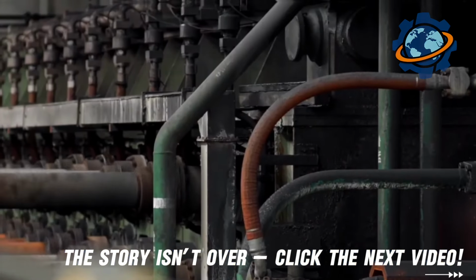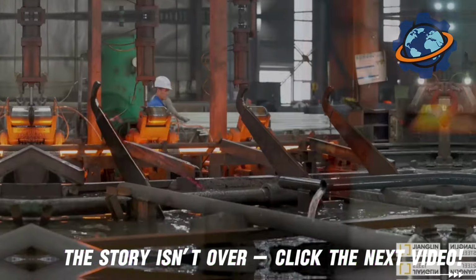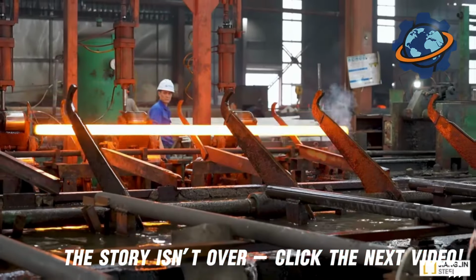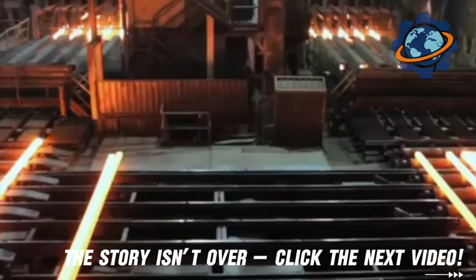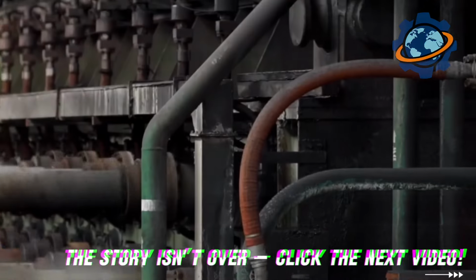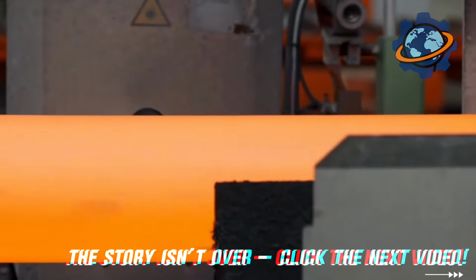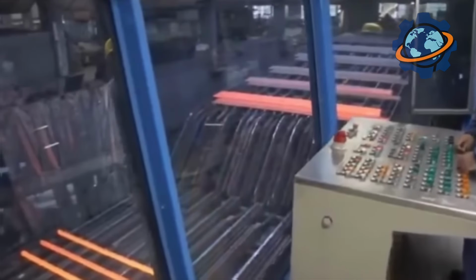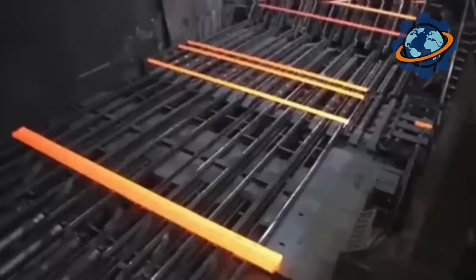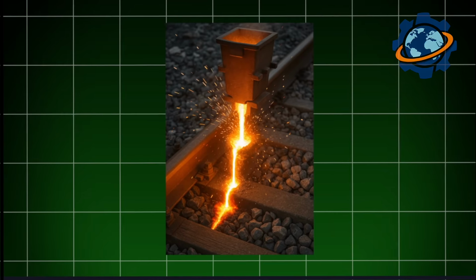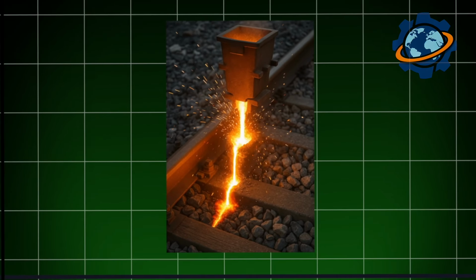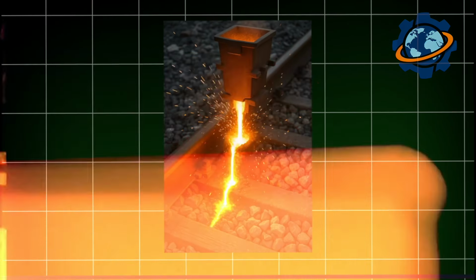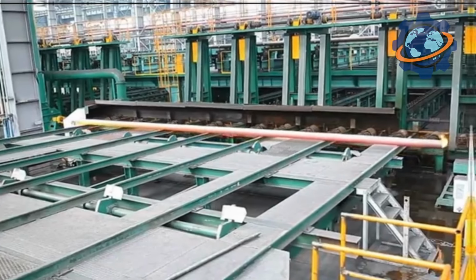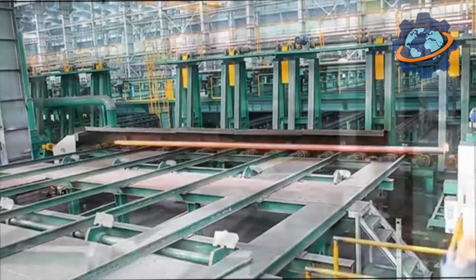To ensure a smooth, bump-free ride at high speed, individual rails are welded into long sections, up to 400 meters without a single joint. The main method is thermite welding. In a special mold between two rails, a gap of a few millimeters is left. A molten steel mixture, created by the reaction of powdered aluminum with iron oxide, is poured in.